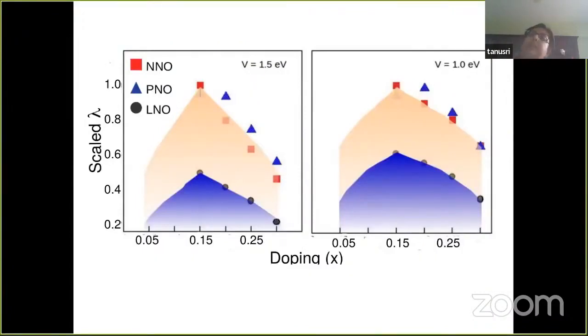So then we calculated the superconducting order parameter as a function of doping. We could not do it for the small doping range because of the technicality of the weak coupling theory. But what we found is that for neodymium and praseodymium, the superconducting order parameter is pretty similar. The strength of the superconductivity is quite similar between the two compounds, irrespective of the value of V we are choosing. But in the case of lanthanum, first of all, we find that the superconductivity is present. It is not that lanthanum becomes non-superconducting, but the strength of the superconductivity is about half or less than half in the lanthanum compound.